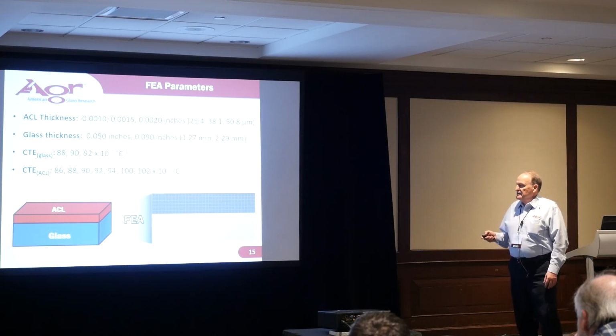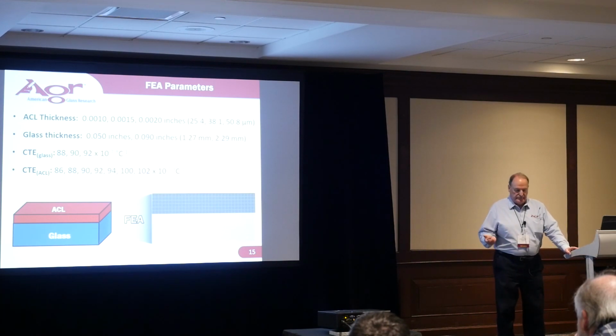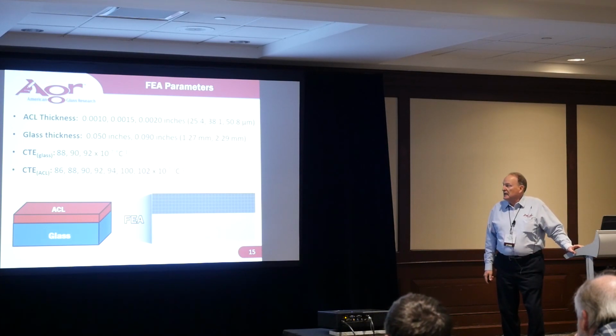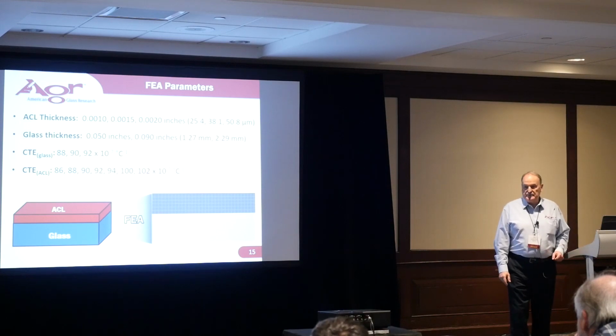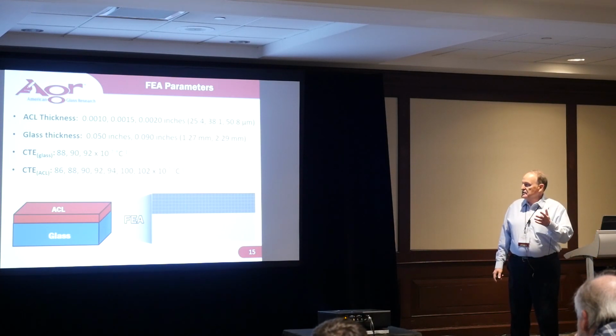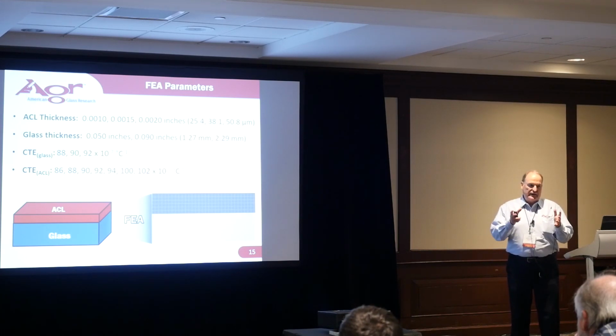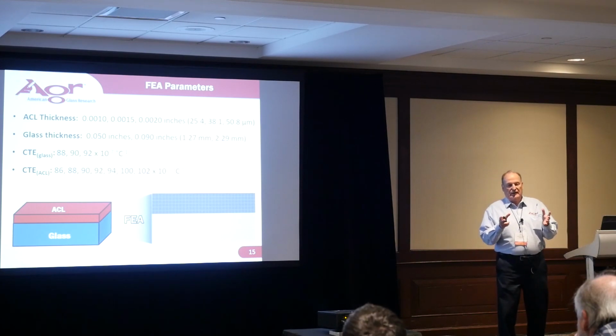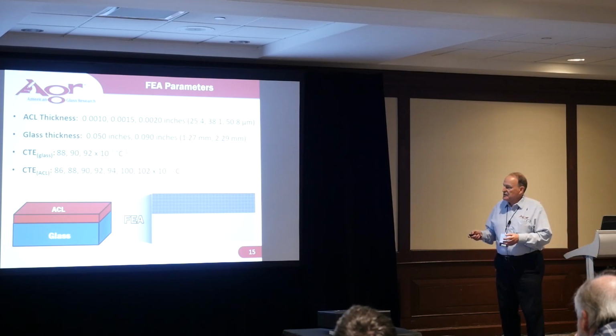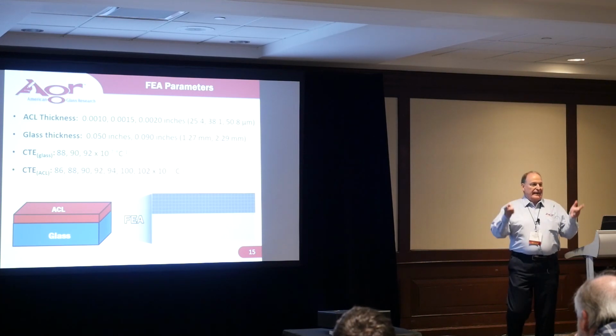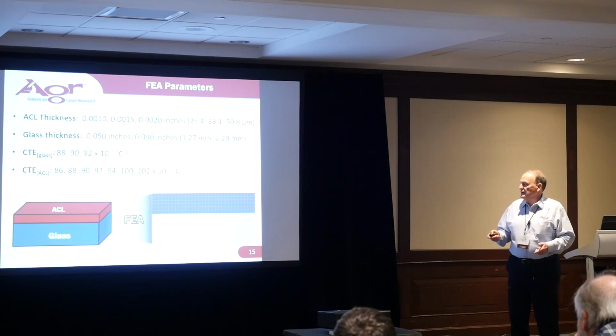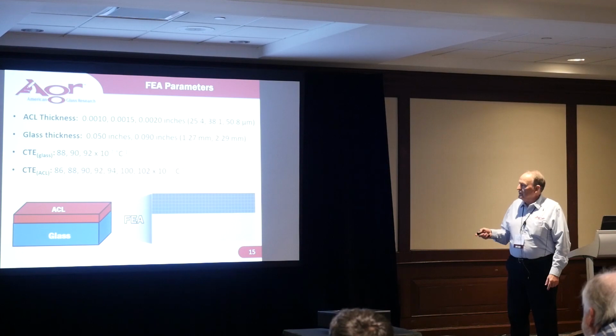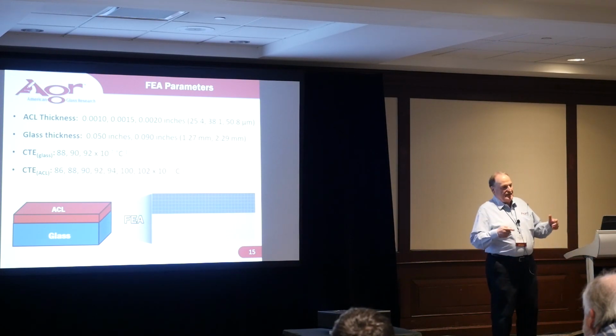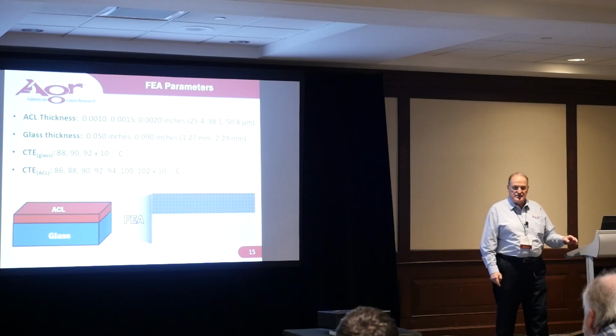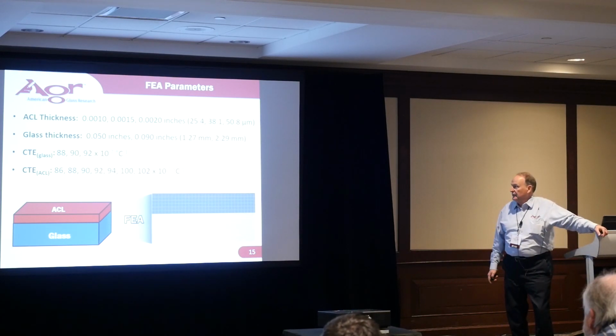Coefficient of thermal expansion of the glass, if you look in the literature, if you look on analytical methodology, soda lime silica glass has a linear coefficient of expansion of around 90. We chose 2 units below that and 2 units above that to try to encapsulate what most soda lime silica glass would show us. Now, for the coefficient of thermal expansion of the ACL, we wanted to bracket the coefficients of the glass. So we chose 2 units below and 2 units above, and had a range in between the two. And then, just for fun, we said, let's get crazy and say, what happens if the coefficient of expansion of the ACL is really high? So we chose 100 and 102.